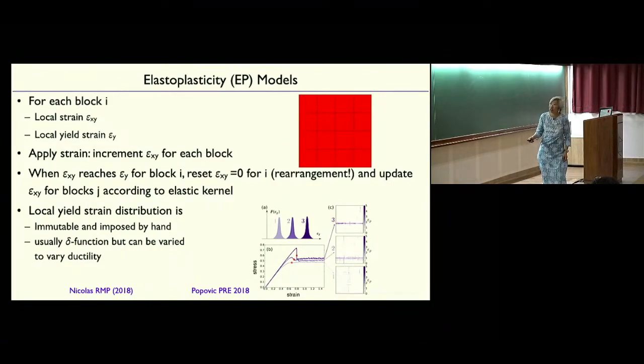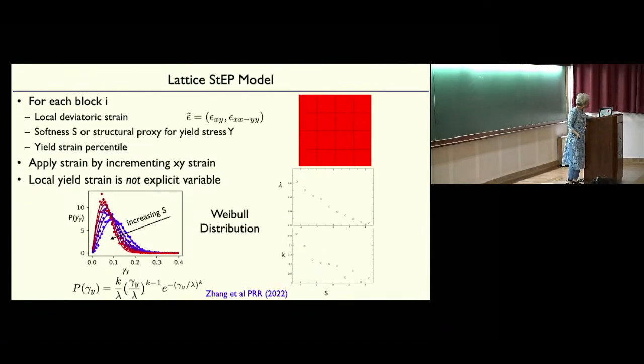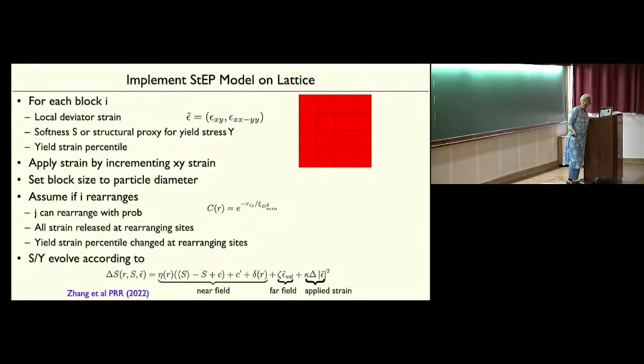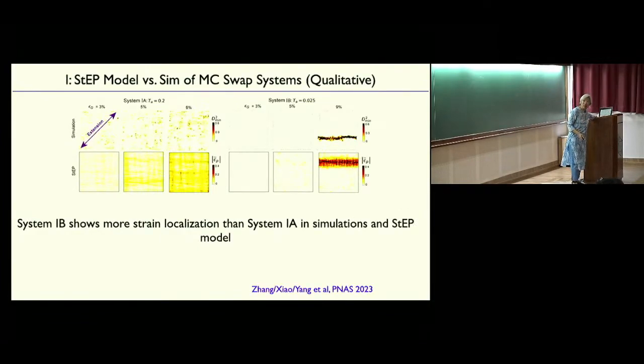And these things, as shown in work by Matthieu Wyart's group, you can tune the system from ductile to brittle by changing the distribution of yield strains, okay? But they put that in by hand. Here, the distribution of yield strains is not put in by hand, it's given by softness. Okay, so yield strain actually depends directly on softness. So I'm not going to go into it, but now we can put this on a lattice. We just put our change of softness. We know, in addition, when you have a rearrangement, not only do you have an elastic kernel that redistributes strain, but you have a softness kernel that changes the softness, right? Both due to the near field effect on spectators and also the far field effect due to elasticity, okay? So you just put that on a lattice, you work it out, okay? No adjustable parameters here. You measure all of these things, okay, either from the experiment or from the simulation.